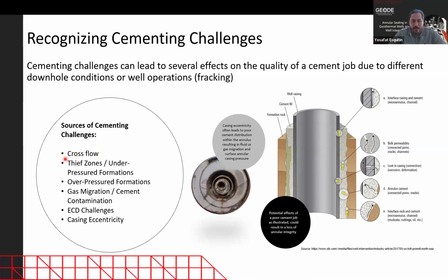And these cement failures can create crossflow, can create different pressure communications between zones or under-pressured formations, gas migration through the annuli, ECD challenges. Basically, when you're pumping that cement job, if the cement job is not planned properly and your column of cement is too heavy, you might induce losses in the well. So there's this ECD that is very critical, and also something that is very important during the well construction is